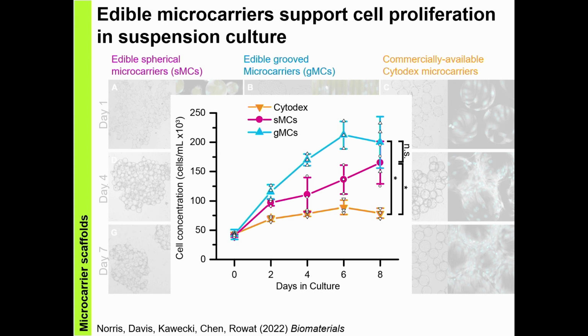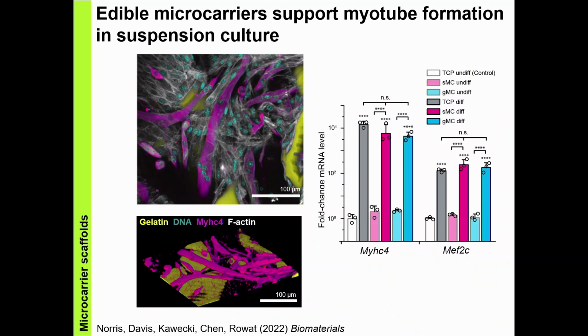We next asked about the differentiation potential, and this image is showing you some myotubes that have formed, labeled with the magenta myosin heavy chain, and you can see that in these 3D reconstructions, these beautiful myotubes, the grooved microcarriers are shown here in yellow, and this is just one representative example. We found similar myotube formation for the spherical microcarriers as well, and we quantified the differentiation by quantitative image analysis and also by looking at the expression of myogenic markers by PCR analysis.